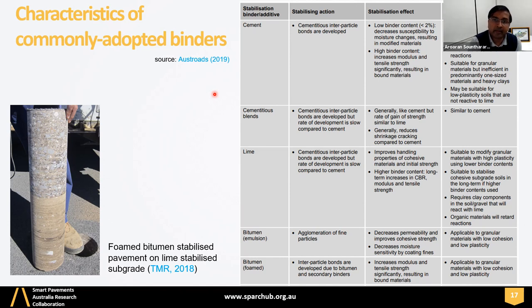So from the Austroads standard, I have extracted the table here, which shows the typical characteristics of secondary binders and the primary binders. I will not go through it in detail because you will be receiving the slides later. If I touch on the cement, cement is commonly used in stabilization, basically in-situ stabilization. As you increase the binder content, it becomes more like concrete, right? Therefore, fatigue cracking will be the predominant failure mechanism. And cement is suitable for stabilizing granular material as well as some marginal materials, right?